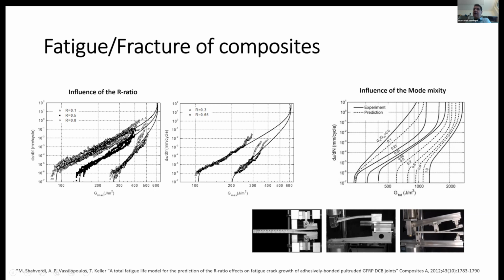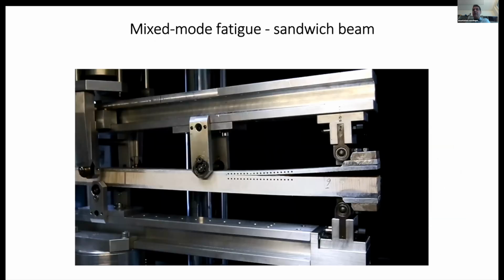What we can extract from these materials is exactly the FCG curves. So remember the Paris law that we discussed before. We have the FCG curve for the material. And you see here that even in these materials and in this behavior, there is an R ratio effect. And there are models, like the models that we had before for the CLDs, to predict this behavior. I will not bother you a lot about this. I will just go to this video here.